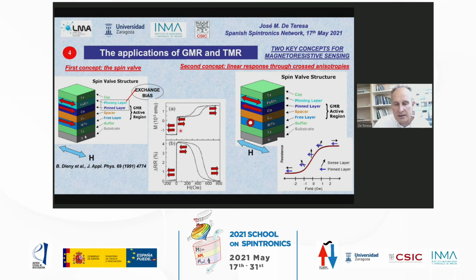So in these magnetoresistive read head sensors you are working in these low fields here, where you will obtain all the magnetoresistance response. Okay, but in order to have this linear response at zero field, you need to introduce this crossed anisotropy. So the free layer is grown with easy magnetization direction perpendicular to the hard magnetic layer. So when you apply the magnetic field, created by the stray fields from the magnetic bits, then you rotate the magnetization of this free layer in a continuous way, so that you obtain a change of resistance at low fields, which is linear. Okay, and this is what is used for sensing with great efficacy.